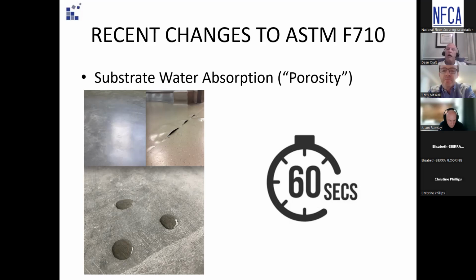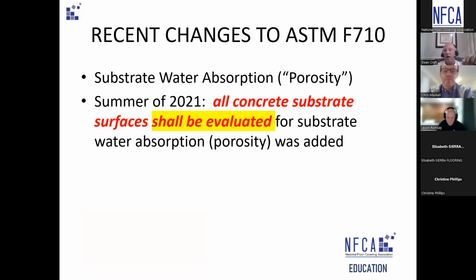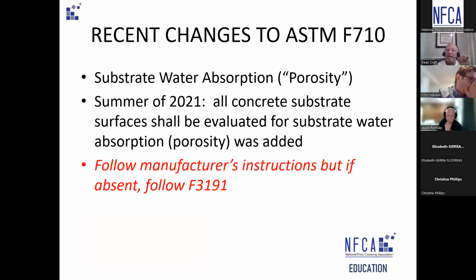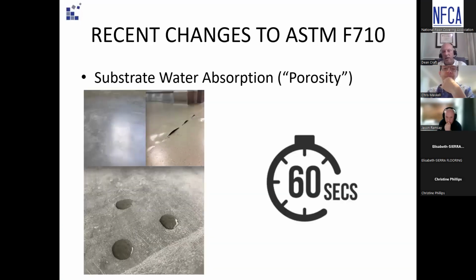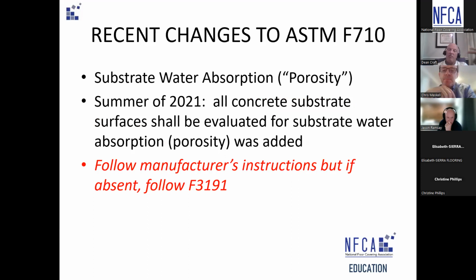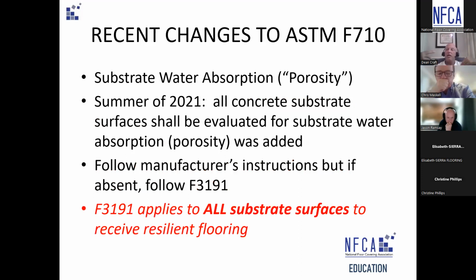It'll give you that uniform surface, but I would just offer then, don't assume that it'll be porous. Even though the standard says all concrete substrate surfaces shall be evaluated, it really needs to be after you skim coat, then test that as well. Because I had one project where the installer, great practice, they skim coated, and to even make it more smooth, they lightly sanded it. So this was a skim coat that had been lightly sanded, and when we did the water drop test, it looked just like the water drop that you did down there lower left there. It looked exactly the same on top of the skim coat. The prep was great, but the surface was still not porous. And had they followed, assuming it was going to be porous, then they would have been installing incorrectly.